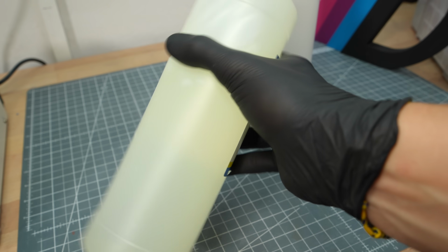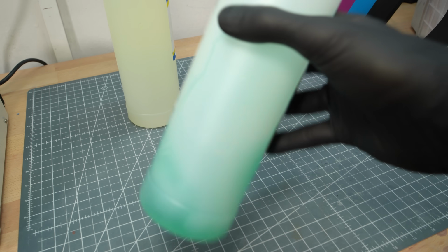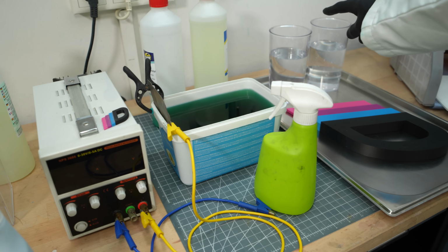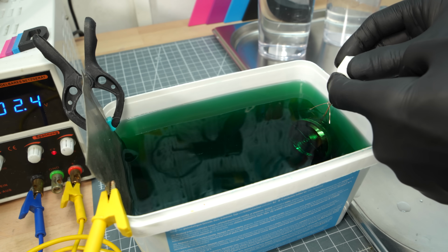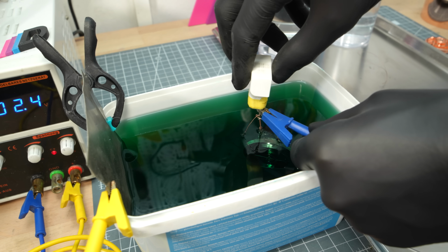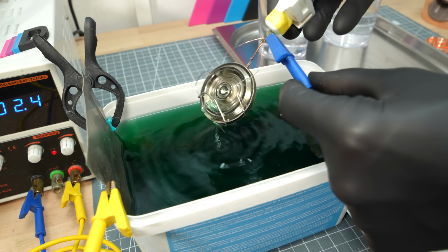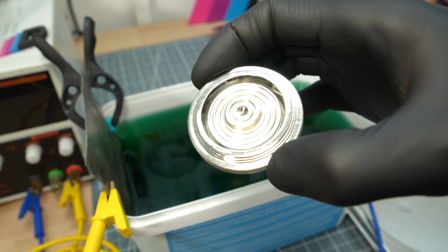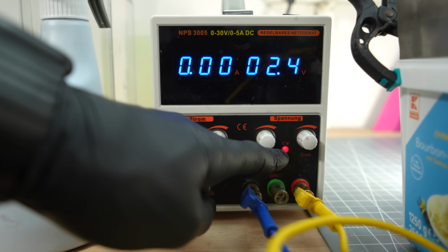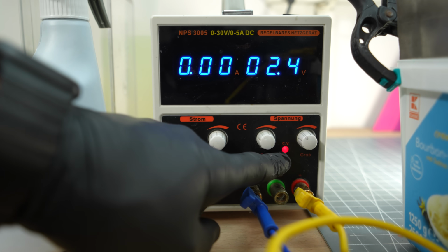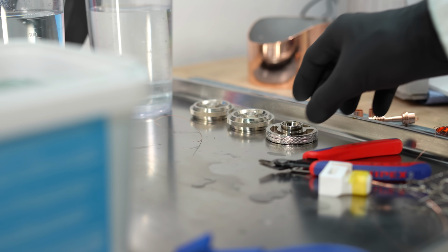Now, bath electroplating with gold and nickel. What can I say? Power, electrolyte, distilled water. I'm using nickel as a barrier layer here, though palladium works too. It's actually better, so use that if you can. I've set the power supply to a constant voltage, just like with the pen plating. Nickel plating takes only about a minute.